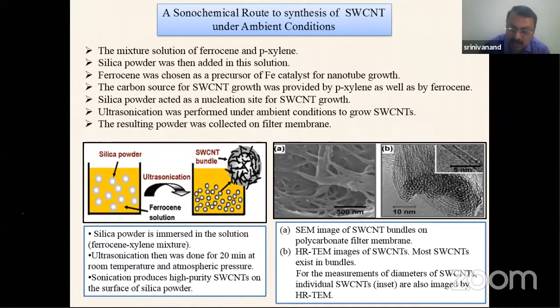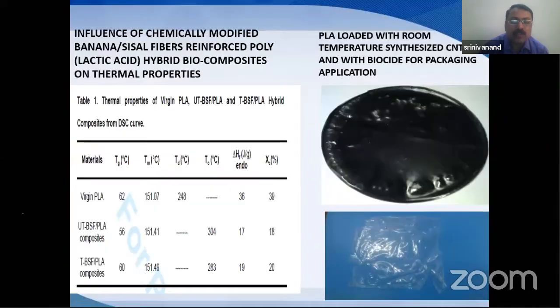The carbon nanotube synthesized in the laboratory is further reinforced with PLA, and we made a film out of it. Surprisingly, when we took the IR, we were not getting any signals, any vibration frequency. Later, we understood that the carbon nanotubes were used for EMI shielding, and that resulted in sending a project proposal to DRDO, which was funded in the year 2017.